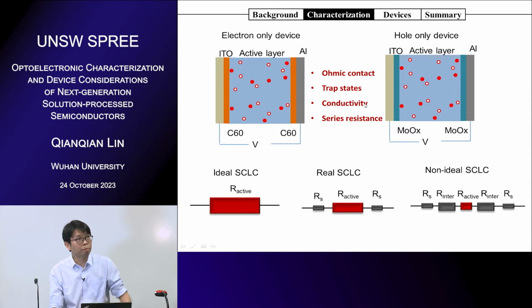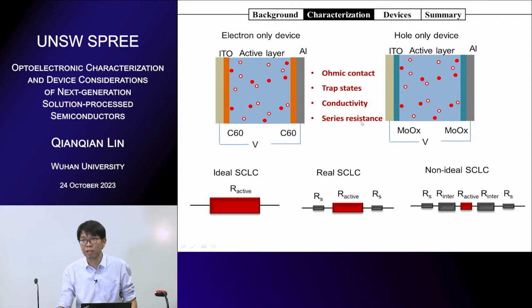But for some materials, they are very thin. For example, perovskite thin films, if you have 300, 500 nanometers thickness, and it's very conductive or slightly doped material, then the resistance of the active layer will be very small. If you have much larger resistance of interlayers, then you don't get anything. You won't get reliable SCLC results from these measurements. So this is not ideal.